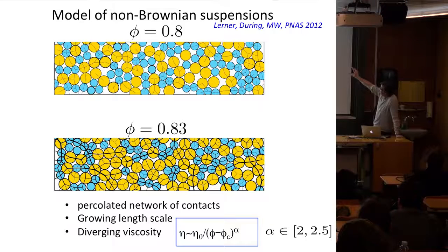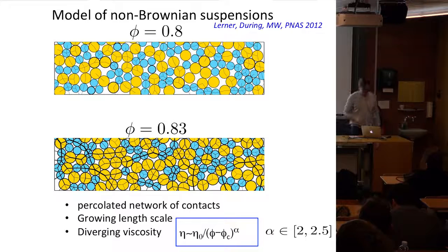What you will see here are movies of systems that are identical, except that the packing fraction is very slightly different. Here, it's just a bit lower packing fraction than there. It's the same strain rate, so you're changing the shape of the box at the same speed. And what you see in black here are the forces between particles. There is viscosity in the... Exactly. So it's over-damped dynamics.